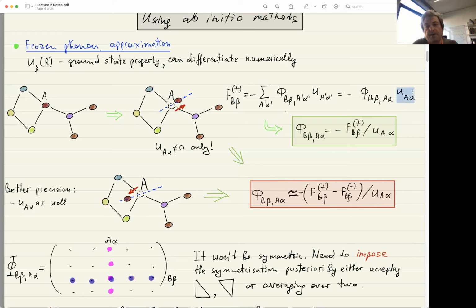And this is a number, a displacement. For example, you can take 0.01 angstrom as a good displacement. You can't take too small a displacement, because if the displacement is very, very small, you will have very bad forces on atoms because of numerical instability. But you can't take a very large displacement either, because then that formula breaks down: anharmonic contributions to the energy start to play a role, and there will be terms in the force quadratic in displacement. So there's some balance you have to take.